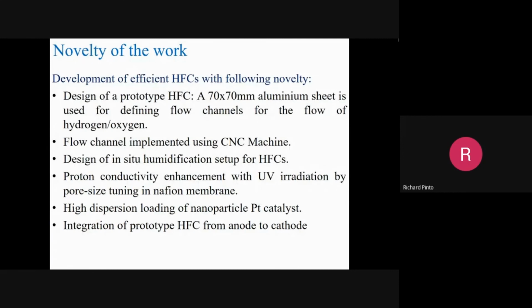Now, humidification I touched upon in the direct methanol fuel cells. Humidification of the membrane is key. And why do we do humidification? We humidify the hydrogen which is going inside. So that humidification setup we also established. And there are a lot of problems there. We solved those problems. Proton conductivity enhancement with UV radiation by pore size tuning in the Nafion membrane. This work was done by Arjun for direct methanol fuel cell. And we used it again for HFCs and again went for another patent application for this. And we got a factor of improvement even in HFC.